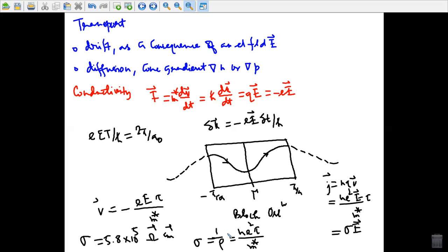Metals have a high conductivity. For copper at room temperature, sigma has the value of 5.8 times 10 to the power 5 ohm inverse centimeter inverse. At low temperatures such as 4 Kelvin, the conductivity is even a factor of 10 to the power 5 higher. The mean free path is then 5 millimeter and thus susceptible to the sample geometry, while at room temperature the mean free path is only 30 nanometer.